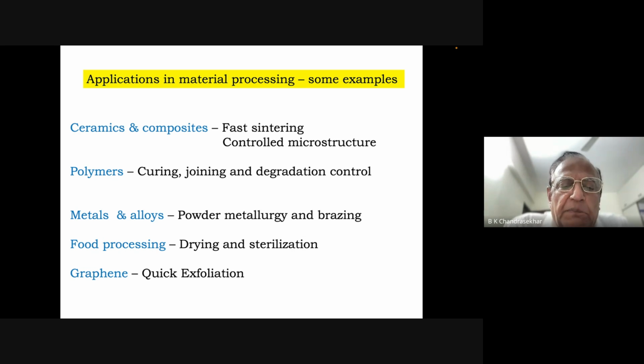It has been found surprisingly that when metal powders are mixed and pressed, when there is a porosity associated with the metals, it has a tendency to absorb microwave rather than reflecting. And this fact was known only in the last about 25 years or so, and therefore a large number of powder metallurgy components are being done using different metals and alloys.